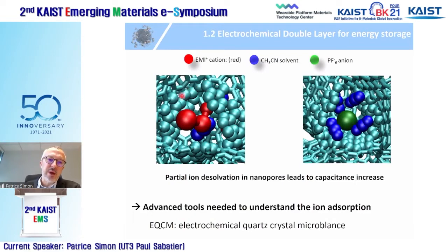This is a sketch I show you here. The gray atoms are carbon, the red one is a cation, and the blue one is a solvent. Here, this is a negative electrode, and you can see that you have a carbon nanopore of about 0.7 nanometer. Cations are entering into these pores of the negative electrode with a partial desolvation. They lose a part of their solvation shell, and they can have access to these pores. Here, the same situation for an anion, a PF6 minus anion. You see this anion is going inside the pores with a little bit more solvent, but still you have this desolvation phenomenon because the pores are smaller than the size of a solvated ion. And this partial ion desolvation leads to capacitance increase.